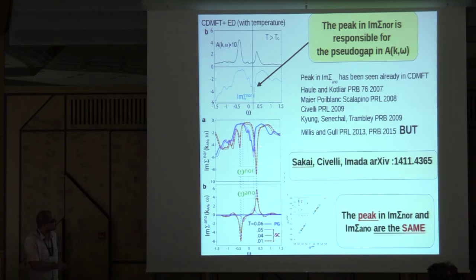Now, when we go superconducting, these are lower temperatures, so we are decreasing the temperature. This peak, the blue line, evolves and is sharper because you go down in temperature, the quasi-particle. So it's like a pole. A pole will double because you have the superconducting gap opening, so you have two Bogoliubov branches. But what was interesting is that if you look at the imaginary part of the self-energy, which is your pairing function, it also has peaks in the superconducting state, and the peaks are exactly the same. We checked it for many temperatures, many dopings. The frequency is exactly the same. So the peak that is creating the depression of spectral weight and the pseudogap in the normal state is smoothly connected to the peak in the pairing. So the shape of the pairing function is strongly dependent on this peak.